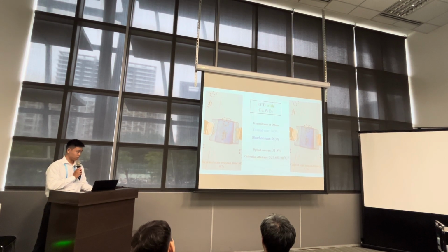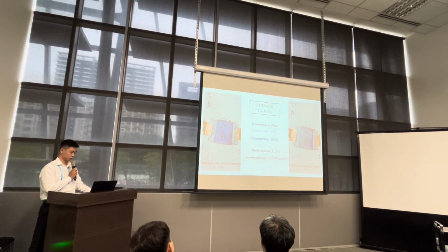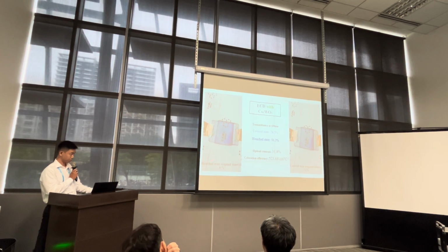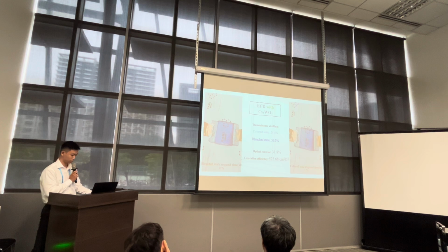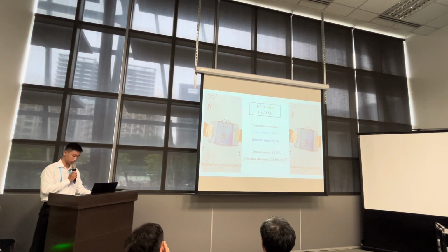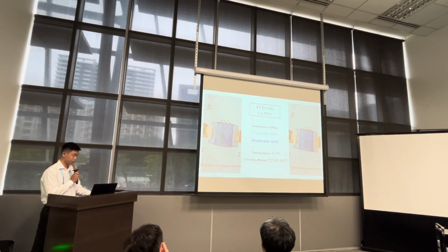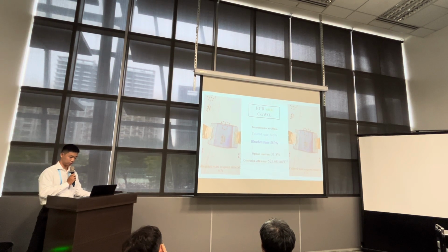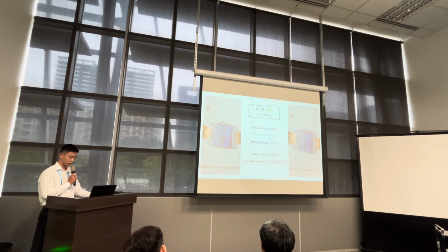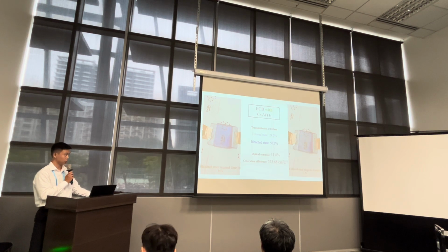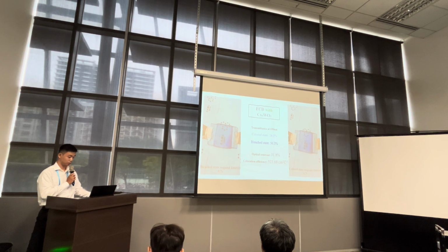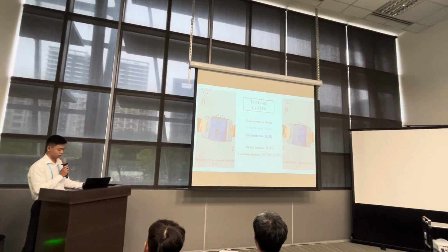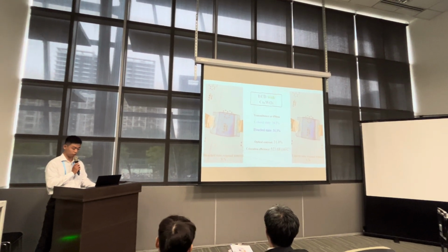Now we're looking at the one with the cesium tungsten trioxide. On both sides you can see a similar response time, but our optical contrast and the efficiency actually get better. The reason for this, we assume, is that the cesium tungsten oxide itself is also a highly conductive material, so it may have improved the conductivity of the thin film.